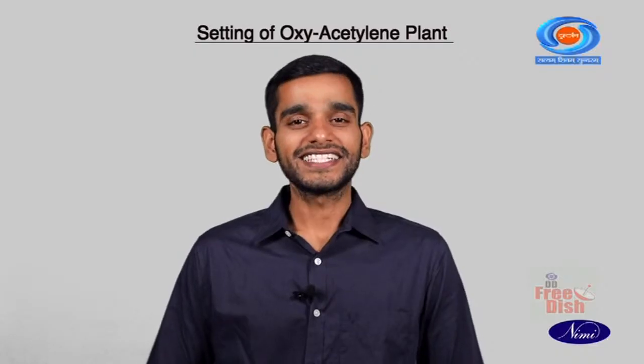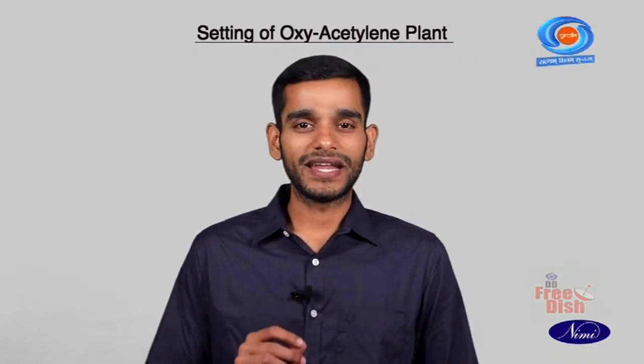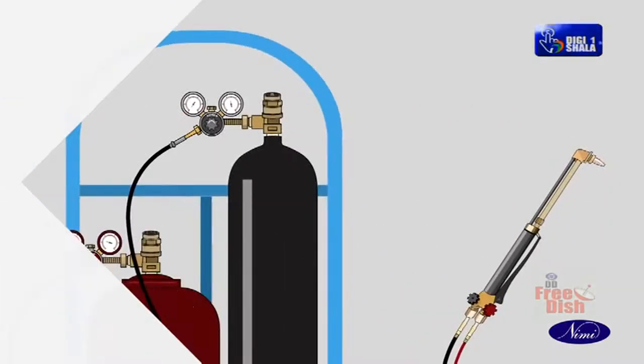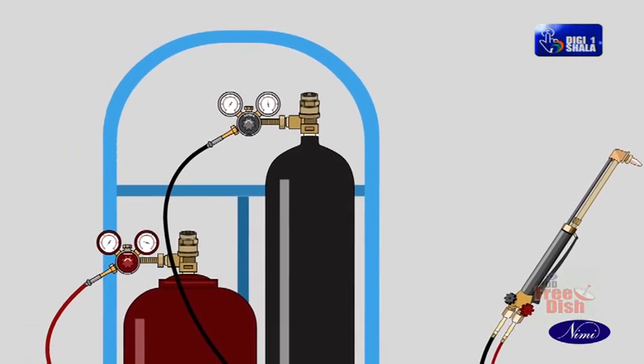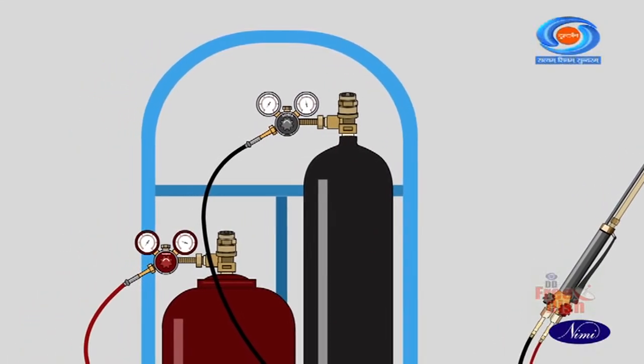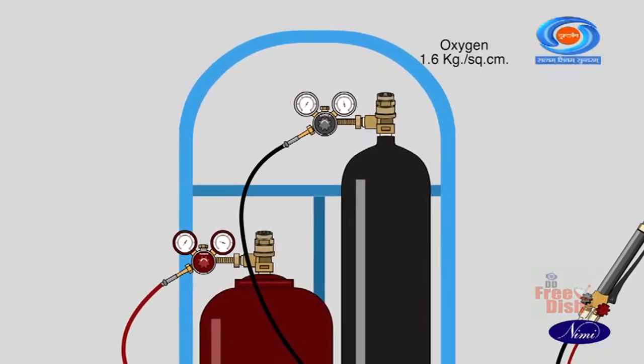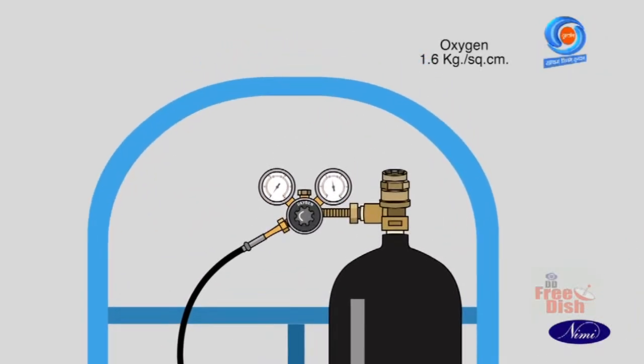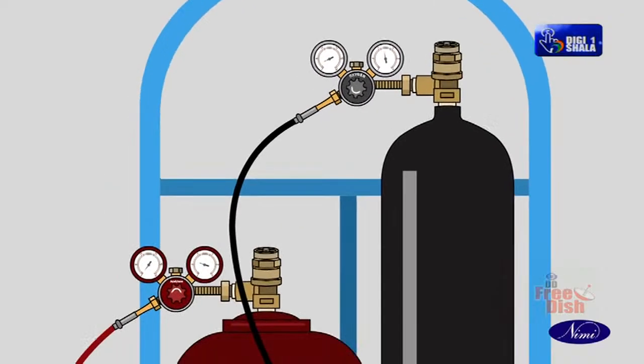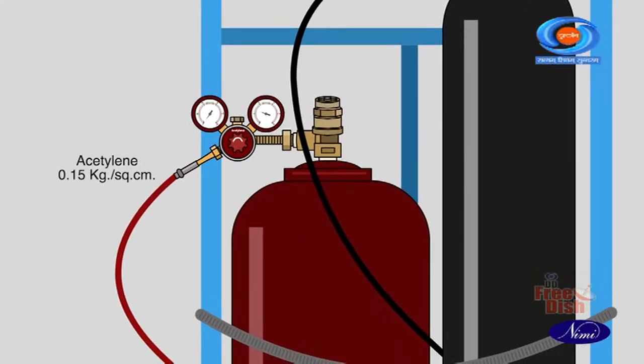Now, let us see about oxyacetylene plant lighting. Open the gas cylinders and set the gas pressures on the regulators. Set oxygen pressure to 1.6 kg per square centimeter and acetylene pressure to 0.15 kg per square centimeter.